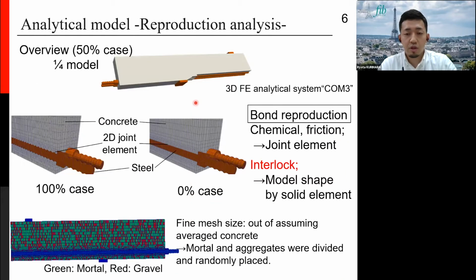In this study, the analytical investigation was conducted from reproduction analysis and an analysis supposing a more realistic state. For analysis, the 3D FE analytical system COM3 is used. This system is based on the smeared cracking model. This figure shows the overall view of the quarter-cut FE model in this study. In this model, the main rebar shape, including lugs, was modeled precisely by a solid model as a steel element and embedded in concrete, for focusing on the interlocking effect well. And two-dimensional joint elements were placed between the steel and the concrete. So it means the interlocking effect is separated from other bond factors, that is, reproduced by the joint element.